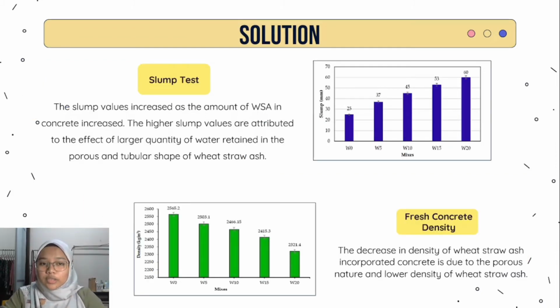We move to the solution. The solution is all about the result that we chose from the journal. For the slump test, it has been shown in the histogram graph. The slump value increased as the amount of WSA in concrete increased. This is due to the effect of larger quantity of water retained in the porous and tubular shape of wheat straw ash. And then for concrete fresh density, the decrease in density of wheat straw ash concrete compared to control is due to the porous nature and lower density of wheat straw ash.